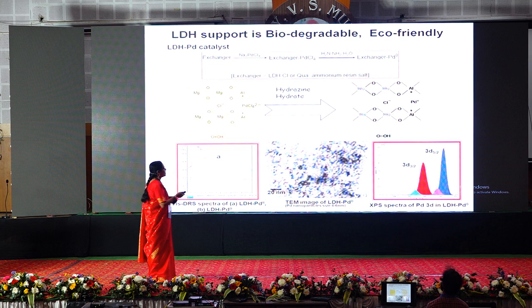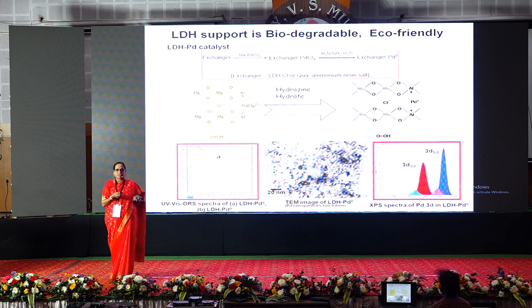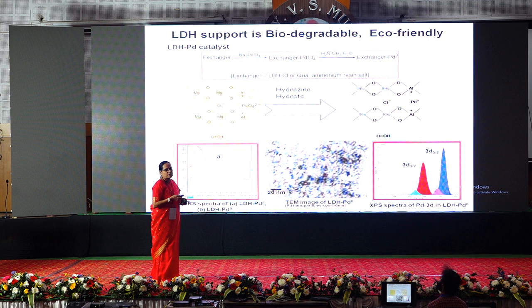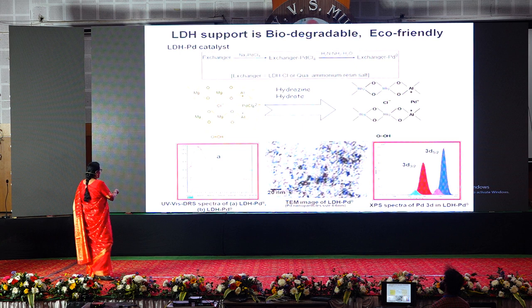Why have we selected hydrotalcite? Because you can see the phosphines are basic, and these hydrotalcites are basic. So we have selected a support which is a basic support. So we put palladium 0 on it, and we have completely characterized the catalyst by TEM and XPS spectra to show that palladium is in the 0 state.